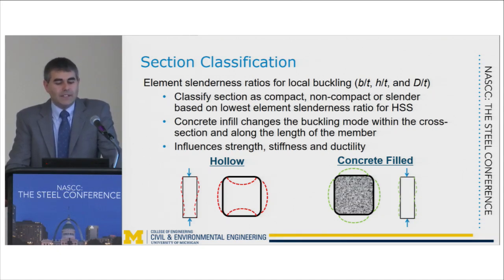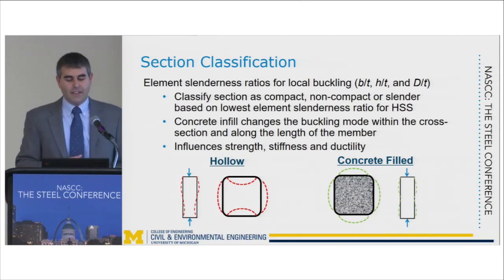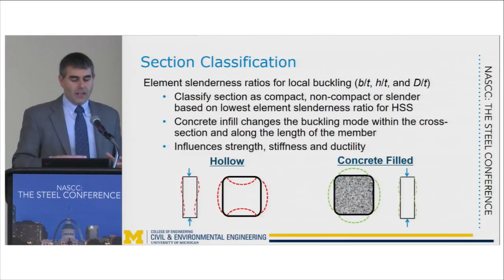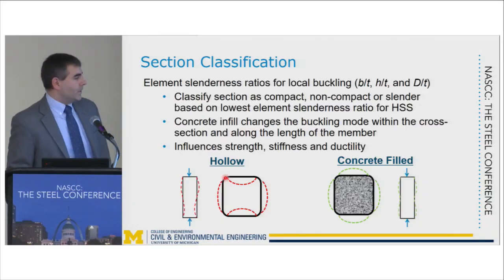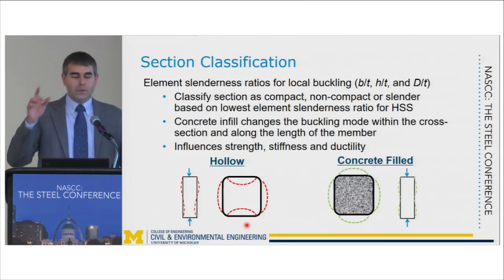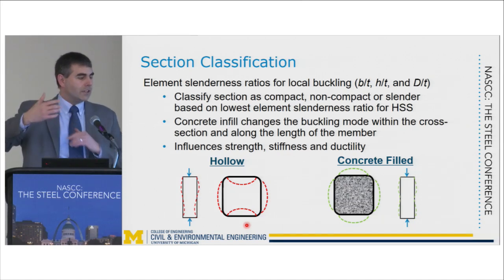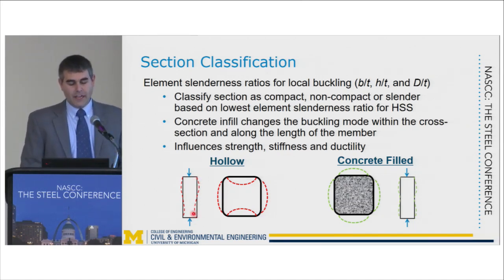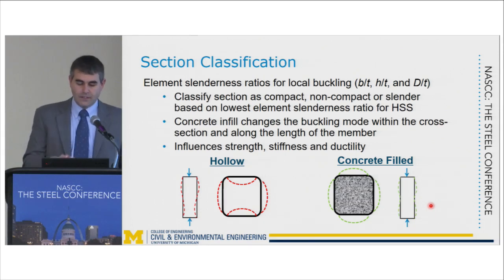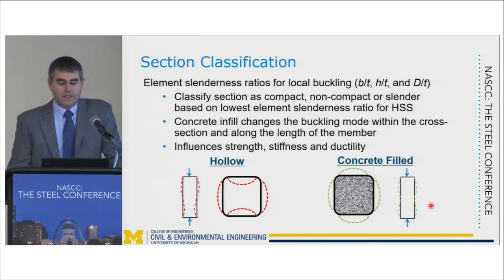Now, the other thing to keep in mind in terms of local buckling is that the concrete infill does actually change the buckling mode, both within the cross-section and along the length of the member. So you can see here, for a typical hollow structural section, two of the walls tend to move outward, and two of the walls tend to buckle inward. As a result, you get this S-type shape or reverse curvature shape along the length of the member. Whereas for a concrete-filled section, because you have that concrete that resists the wall moving inward, all the walls end up buckling outward, like you see here in the figure. And you get more of an hourglass shape along the length of the member. This buckling mode tends to lead to a slight increase in the moment of inertia and some more stable post-buckling behavior that you can take advantage of.